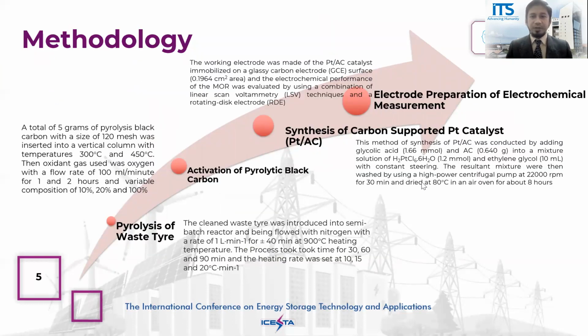In pyrolysis, the condensed product was kept inside liquid storage, while the vapor that was not changed into liquid was channeled to gas storage. The pyrolysis process was conducted at atmospheric pressure. The sample, that is the solid material, was removed from the reactor after pyrolysis was completely finished.